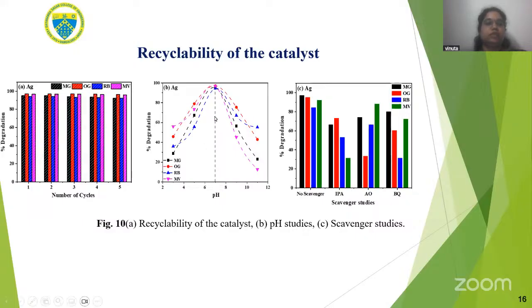So next, this plot explains that the pH of the absorption media plays a crucial role in influencing the absorption rate. Here we have used a different pH range, that is 3 to 11, acidic to alkaline pH, because for water treatment or dye degradation, we can have samples of any range, just to check what the range of pH is. We have used different pH.